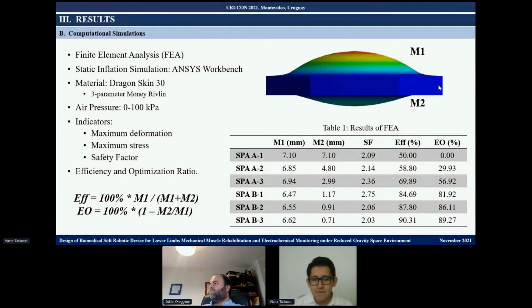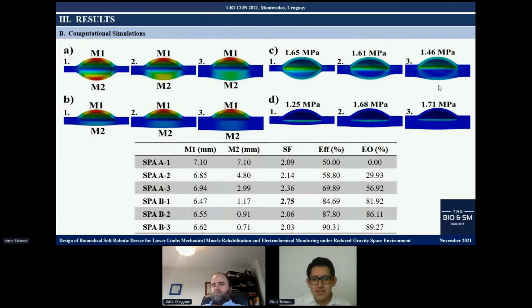But in this picture, you can see a reduced and attenuated displacement on the one side of the actuator conformed by Dragon Skin and Ecoflex. In addition to having the PET foil, with this result, the actuator proves to be able to concentrate most of the energy in the desired direction, generating a higher free displacement to perform better stimulation. Therefore, it will have increased surface contact over the skin, thereby having a deeper effect onto the target muscles, without risking epithelial damage.